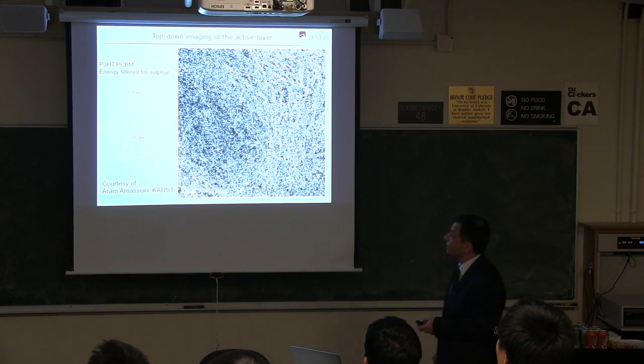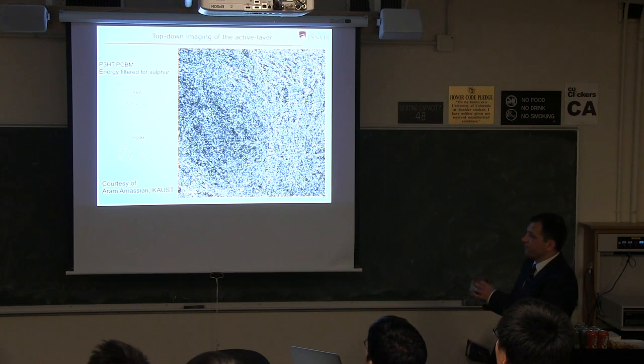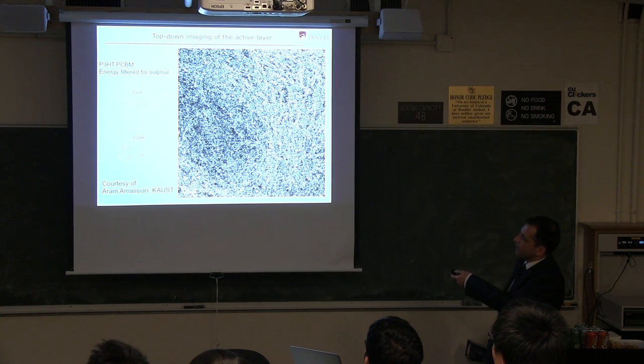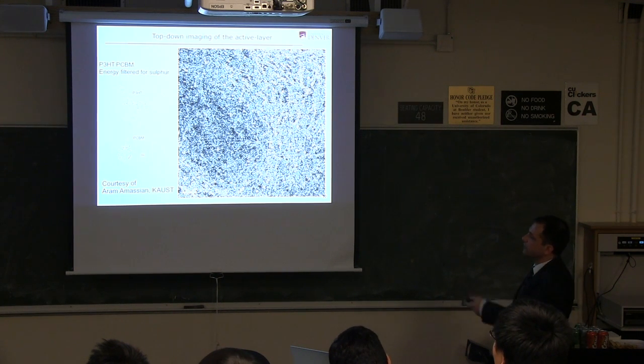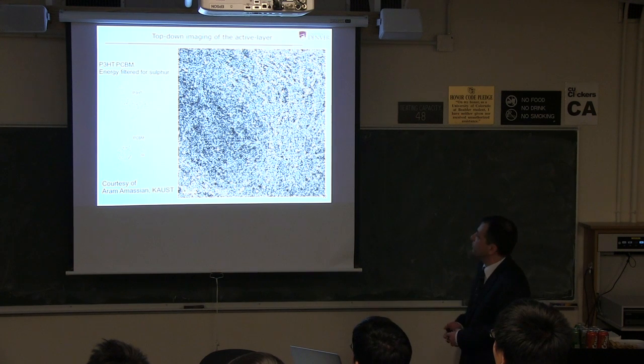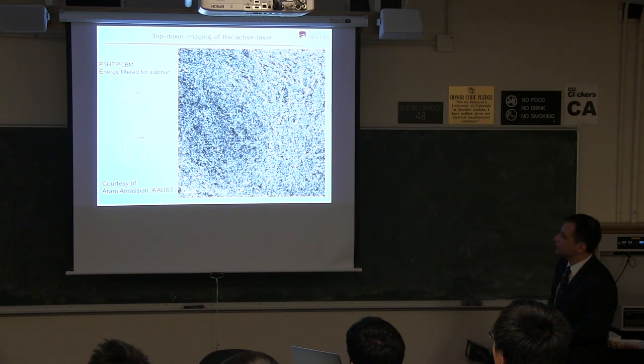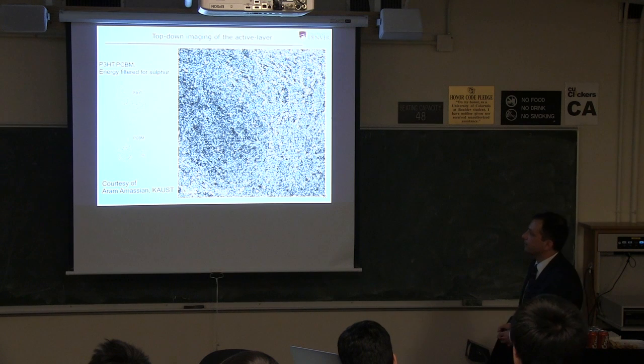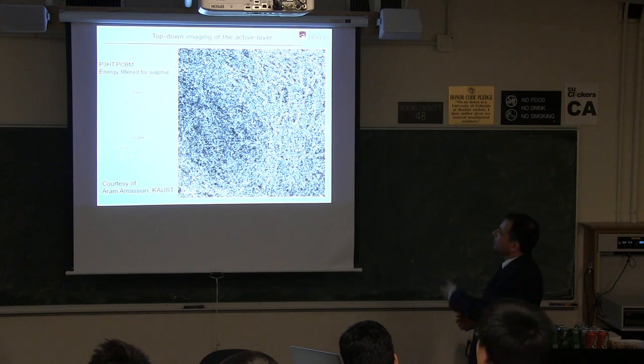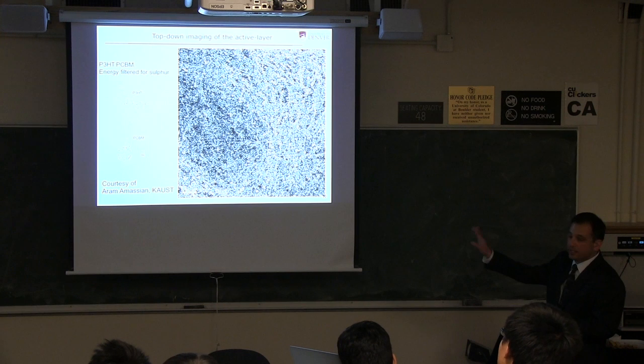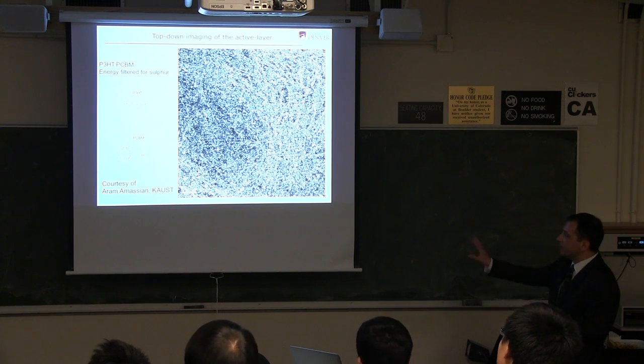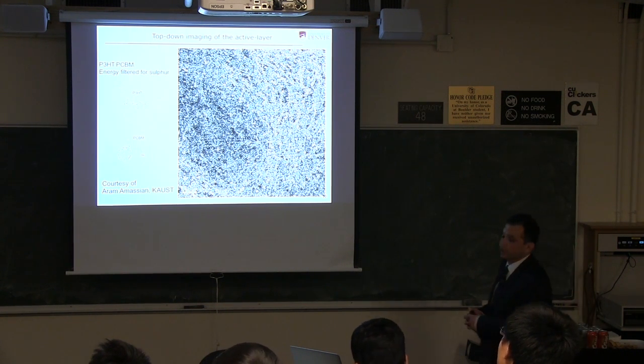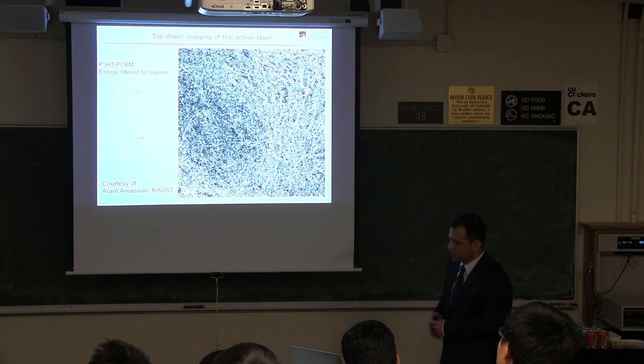We can also, using a TEM, filter the energy of the TEM and look for specific elements. And in this case, if we look for the sulfur, which is on that position of the thiophene, then we can see selectively the polymer material versus the fullerene material that has no sulfur. Well, what you see is not too much. It's a fairly uniform dispersion of the sulfur throughout the material. But I think if you look carefully, there are some fluctuations and periodicities in there, and there's some data to be extracted. We haven't done that with this image, but we have some better images that we're working on to see what is the distribution of material.